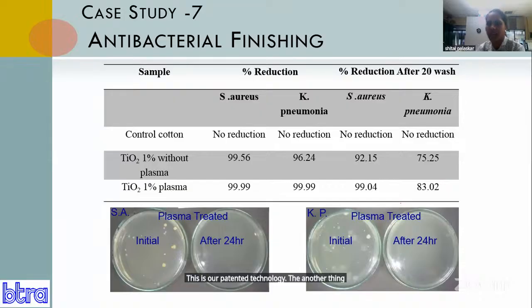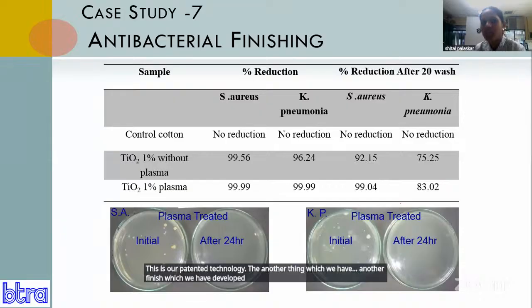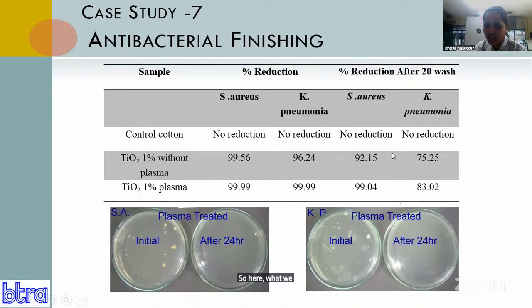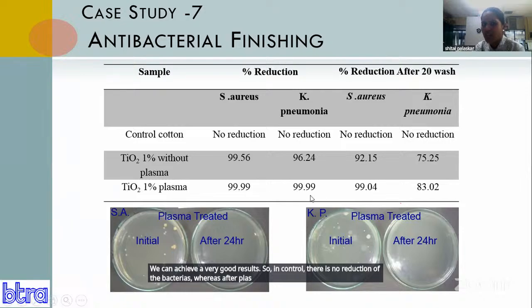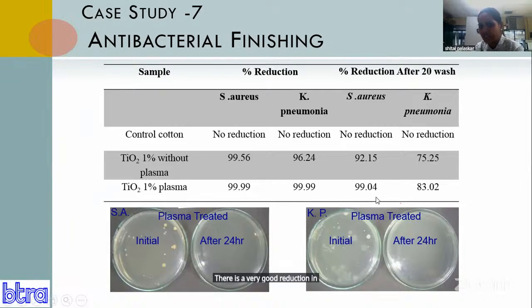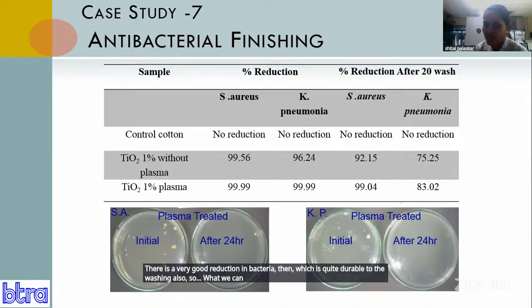Another finish which we have developed is antimicrobial finishing using plasma technology. When we use the plasma treatment, we can achieve very good results. In the control, there is no reduction of bacteria, whereas after plasma treatment, there is a very good reduction in bacteria, which is quite durable to washing also. So we can say that after plasma treatment, the efficiency of the material to become functional is improving, and the durability of this functional finish is also improving.